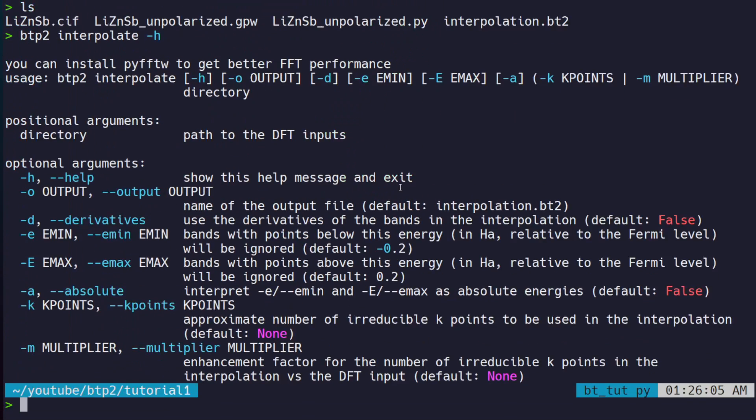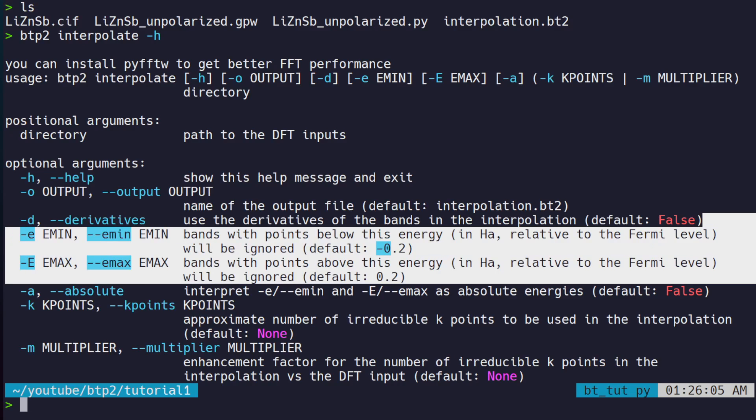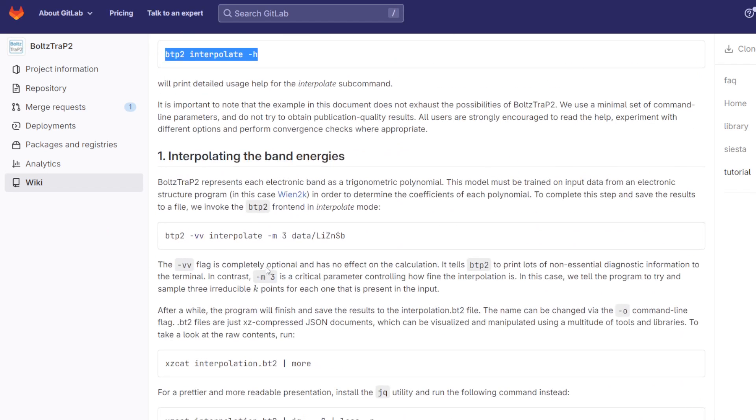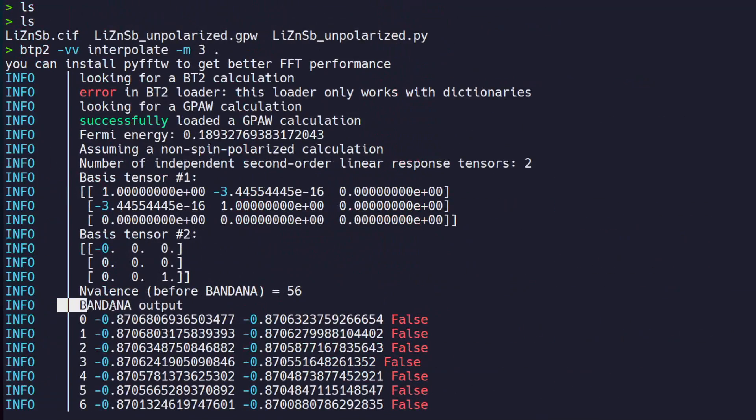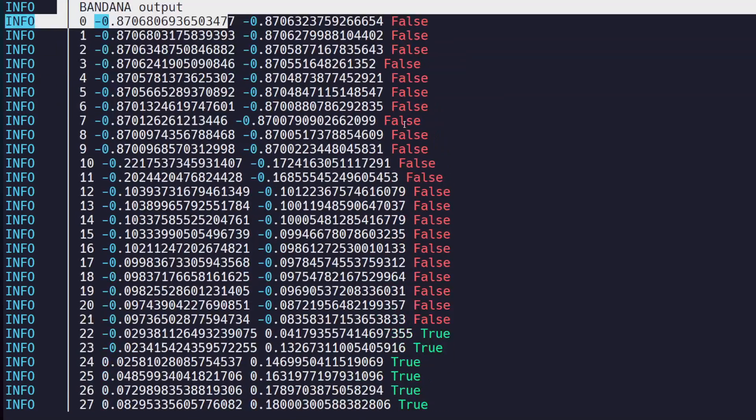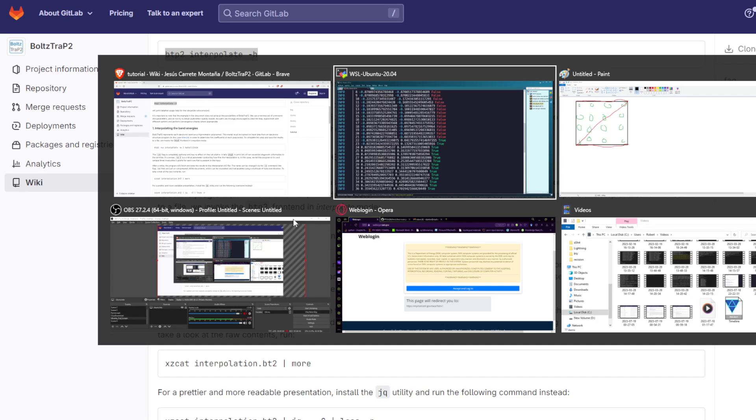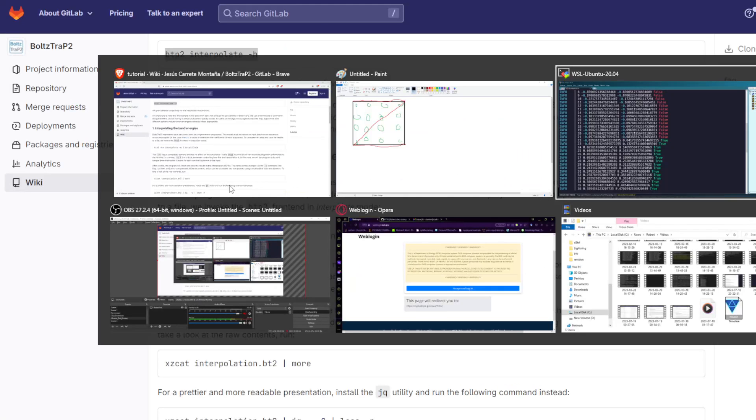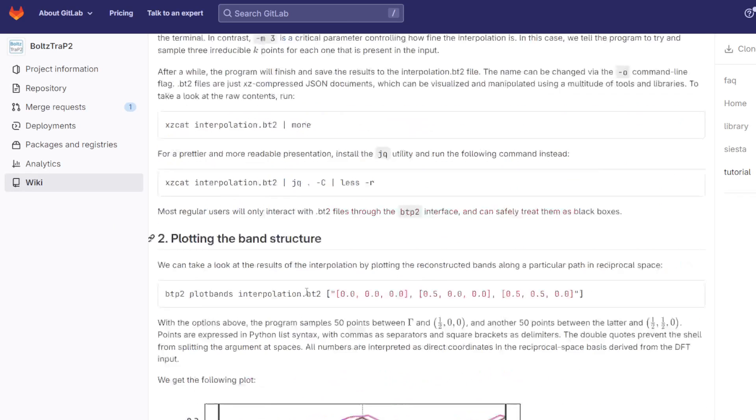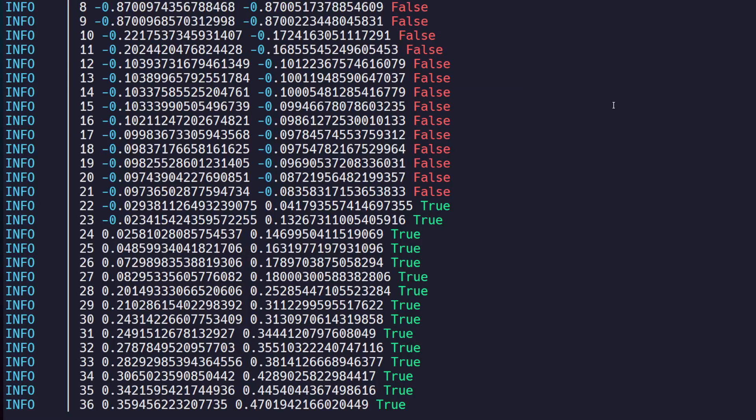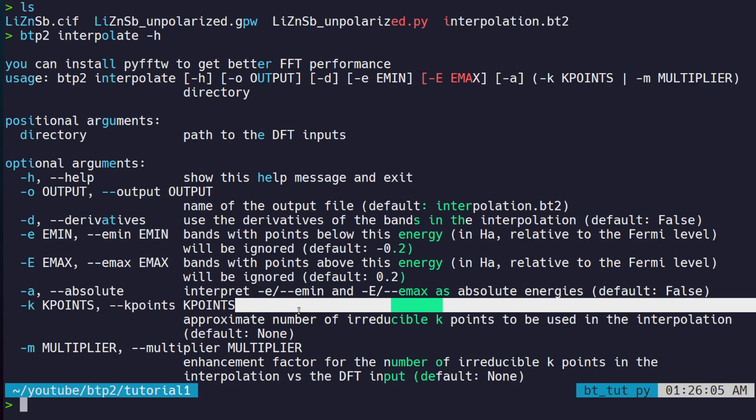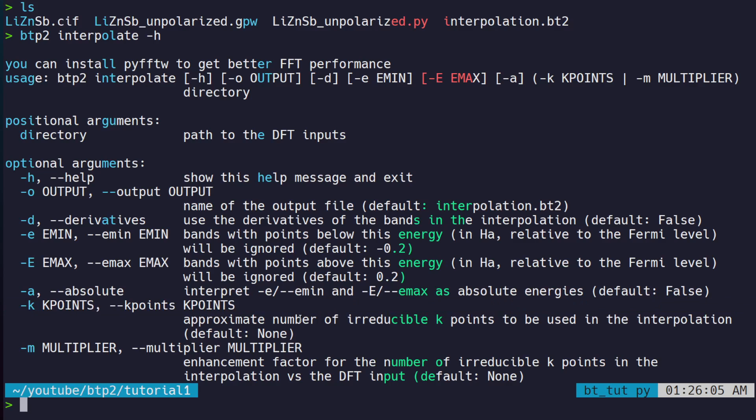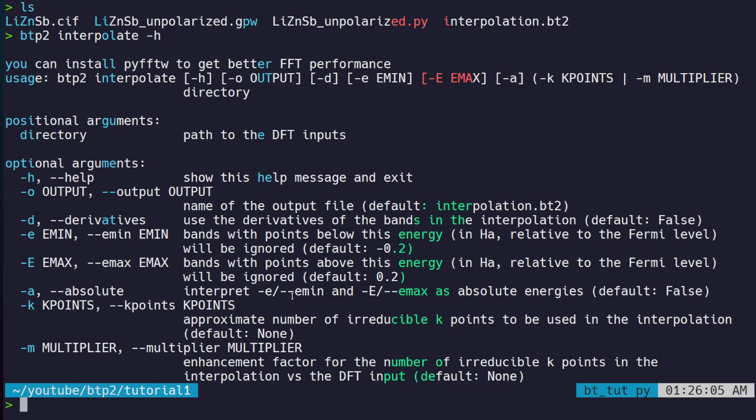These have to do with how many bands end up being included, and you can see this in the bandana parameter. When you see bandana in here, it tells you which bands of your DFT data are included and which are not. Basically, 0.2 is the cutoff, so any band that is at some point within ±0.2 gets included. You can also manually specify how many irreducible k-points, but they're really not necessary.